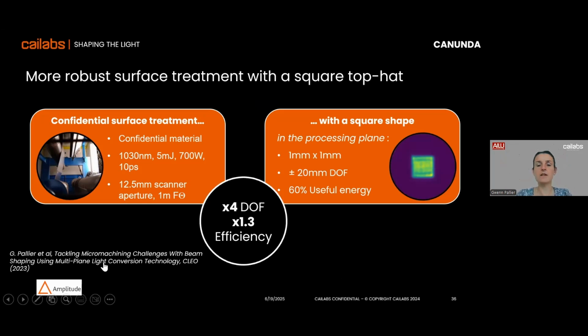So in that case, we really tried to optimize having a square with a fixed setup. The square was 1 millimeter by 1 millimeter. And our customer really needed to have a high depth of field because they are processing very large parts and they do that very fast and those parts are not so precise. So if your depth of field is too small, somehow it's impossible to have this roll-to-roll process.